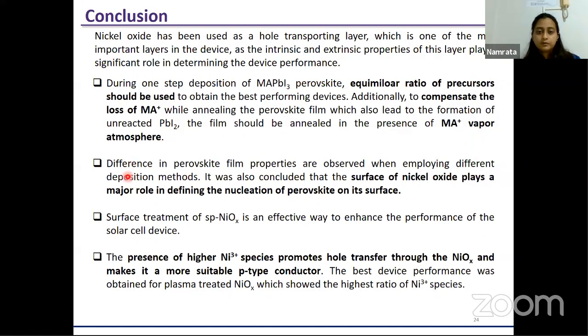And differences in perovskite film properties are observed when employing different deposition methods. It was concluded that the surface of nickel oxide plays a major role in defining the nucleation of perovskite on its surface. And the surface treatment of sputtered nickel oxide is an effective way to enhance the performance of the solar cell device.